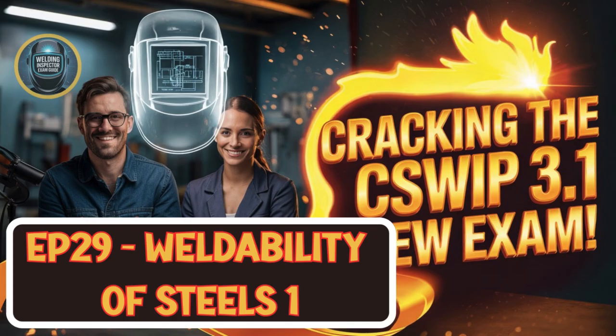Yeah. First, weld metal composition. The absolute key here is to avoid contamination. Sulfur and copper are particularly nasty culprits for this. Where do they come from? Sulfur often comes from oil, grease left on the joint, or sometimes from less refined parent steel grades. It forms iron sulfides that stay liquid at very low temperatures relative to the steel.